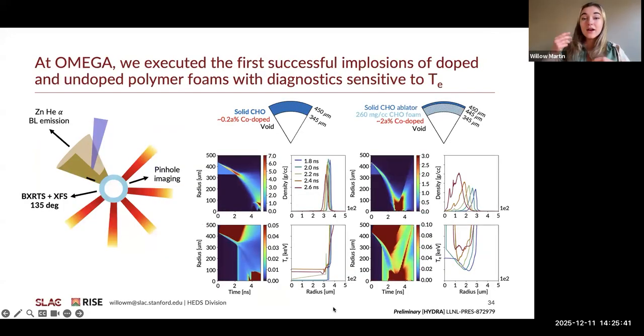Namely, the diagnostics that we fielded in the first stage of our campaign at LCLS, X-ray Thomson scattering and fluorescence spectroscopy, were also fielded at Omega last year to characterize imploding targets that were directly driven with about 14 kilojoules of 351 nanometer laser light delivered by the 60 shaped drive beams at Omega.